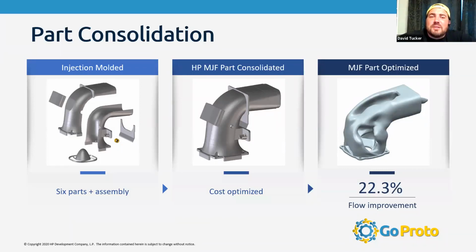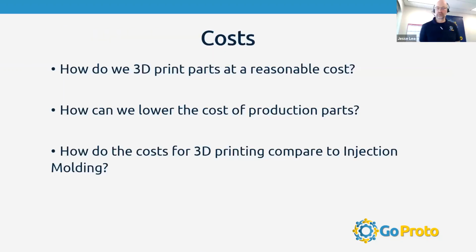And I like this question that I'm looking at, so I'm going to steer it: the one about issues with moisture. So from a polymer standpoint, PA12 isn't hygroscopic. It doesn't absorb a lot of moisture. Not compared to nylon 6. Nylon 6, yeah. And also with polypropylene, like zero moisture absorption. Those two materials, you can put them in moisture. You can put them outside of vehicles, and as they get wet, they're not going to change mass. They're not going to change properties. Very, very limited moisture. Great question, a great answer, thanks.